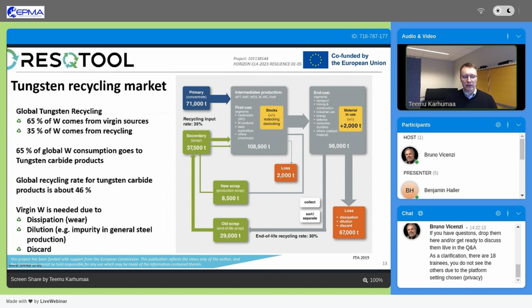But we still really need virgin tungsten in the supply chain, because, for example, during the drilling of rock in the mines, the hard metal parts really wear. And then we lose some tungsten in steel. Let's say lose, it's an incorrect word, but it is diluted in the steel, and if the tungsten-containing steel goes for the next round into non-tungsten-containing steel, this tungsten is lost from the loop.